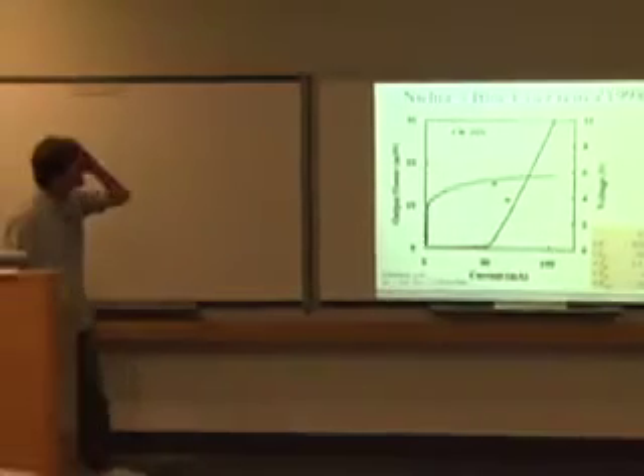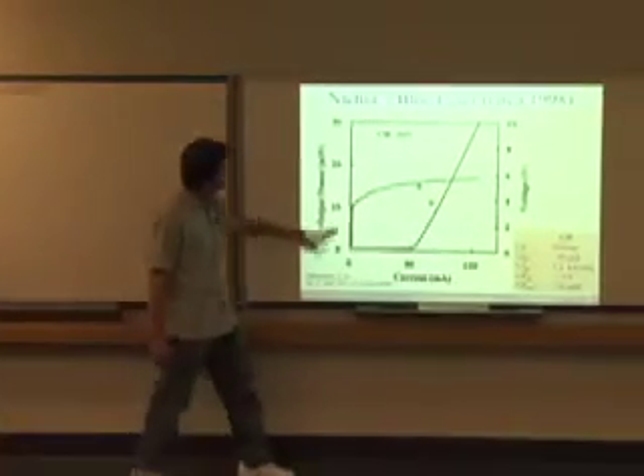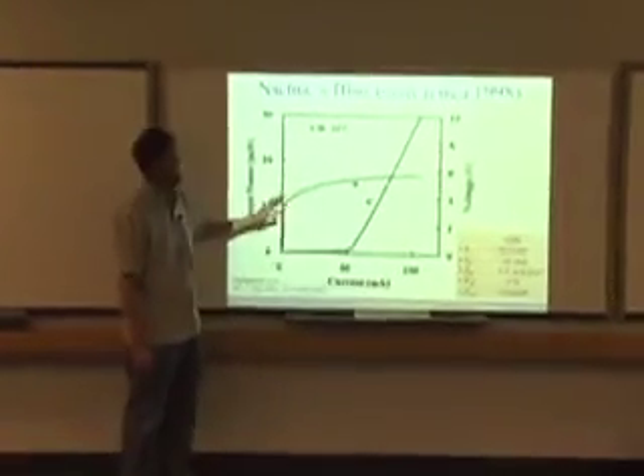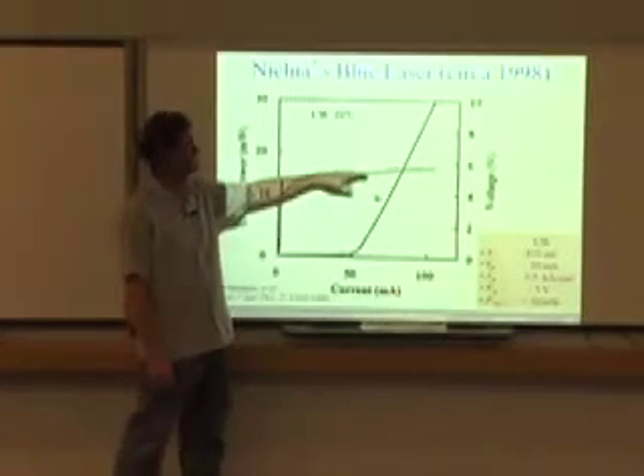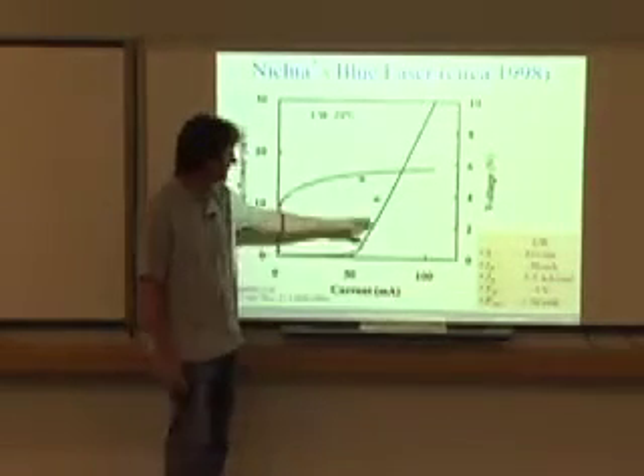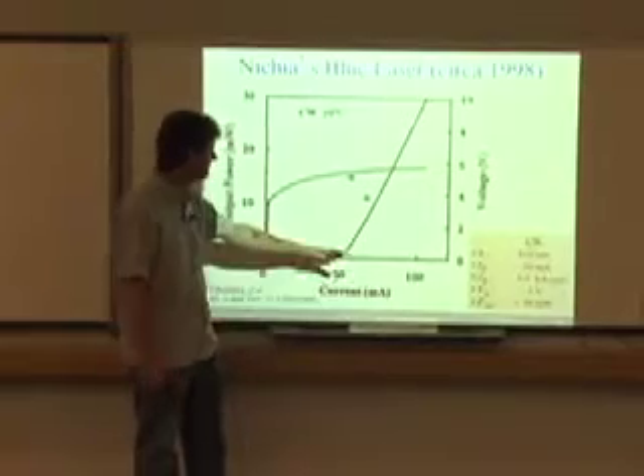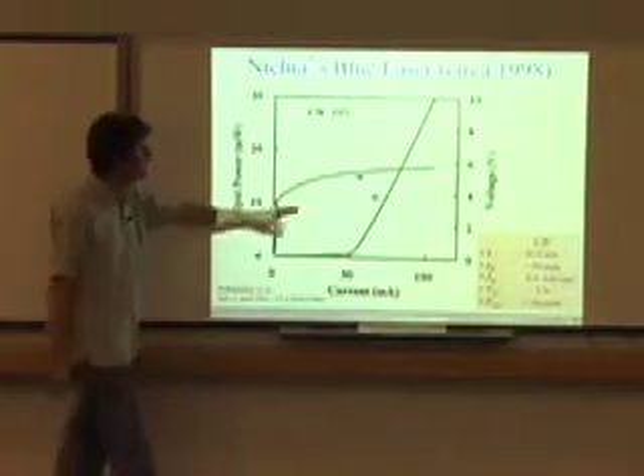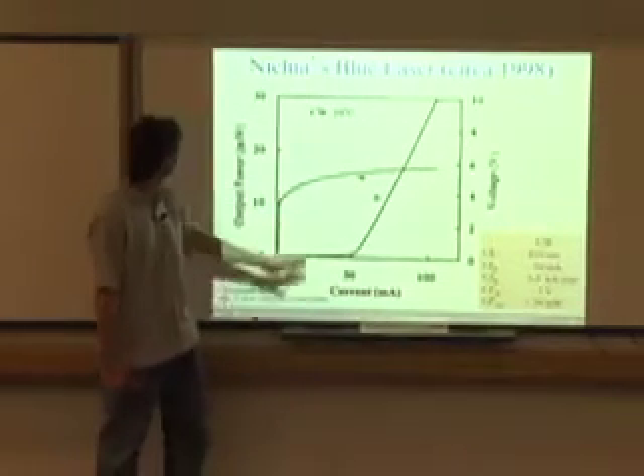This is an example of your blue laser with the LI curves and LIV curves, and look at the voltage here. Looking at 5-volt thresholds, 50 milliamp current thresholds, and output power greater than 30 milliwatts. Didn't even bother to mention what the peak was. It was just, whatever, it's good.